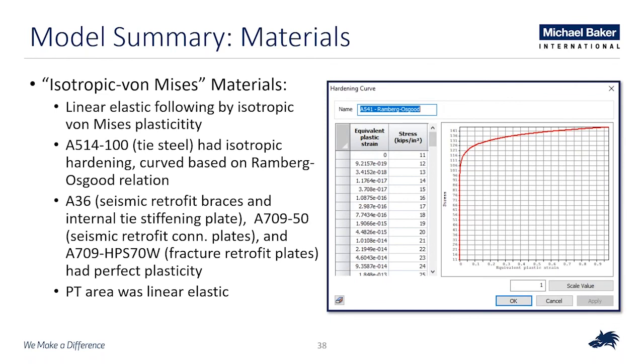Regarding the material models, we use isotropic von Mises material, so your typical metal plasticity, J2 plasticity. It's a linear elastic relationship followed by isotropic hardening. For the steel used in the tie, that is the A514 100, also known as T1, we use isotropic hardening. The curve was developed based on a Ramberg-Osgood relationship.